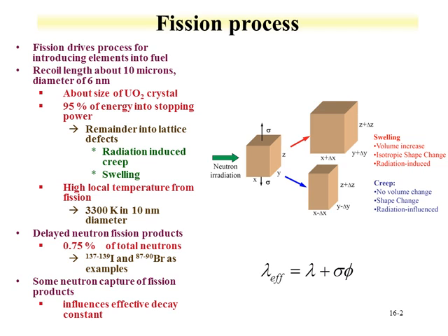Now, in the fissioning process, and we reviewed this earlier, fission products will recoil about 10 microns in UO2 with a diameter range of about 6 nanometers. So imagine there's not a lot of straggling, very little distribution along the width of this recoil. So this happens to be of the size of a UO2 crystal. We already talked about Frenkel pair production.